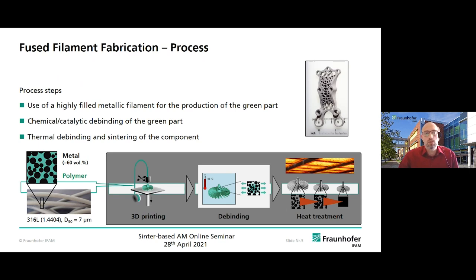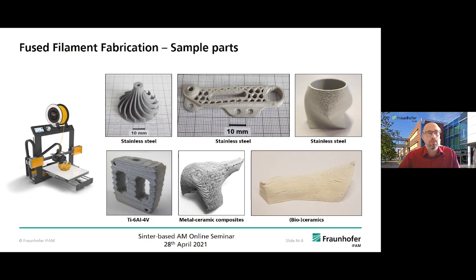And so we don't use these plastic filaments, but of course, powder filled feedstock filaments. Of course, those have to be able to be processed in this manner, which is not always possible with the feedstock, for example, used for metal injection molding. But other than that, you print the part and also have a debinding and sintering step, as was shown also previously. Here you can see some sample parts, not only metal ones, but mainly stainless steel, as it's the workhorse for development, as basically for all processes.